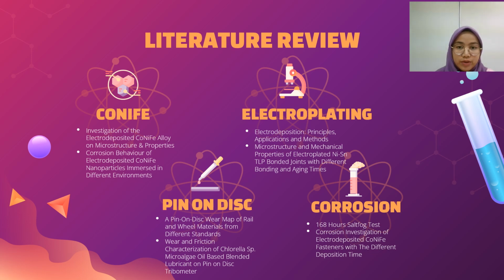While for corrosion behavior, the result shows that in alkaline environment, CoNiFe nanoparticle produce smallest particle size, less oxygen content, and less corrosion rate. For electroplating, a study entitled Electrodeposition Principles, Application, and Methods shows the capability of electroplating in fabricating one-dimensional nanostructure, such as nanorods, nanowires, and nanotubes.